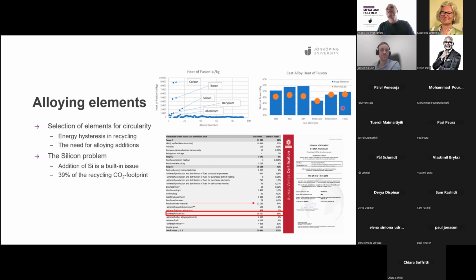And if you look at the different alloys, you have the international materials or American standards with A380, A383, A384. So if you take the Neumann-Kopp rule, just by rule of mixtures, you get very high. And of course, there are some entropy effects. So if you take thermal data, it's slightly lower here. And if you take the real cool alloy that was mentioned, it's significantly lower, and the real green is also lower.